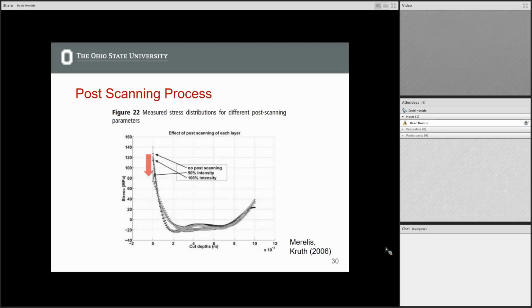However, with 50% laser power, they did see a reduction in the maximum residual stress that was in the part itself. This paper was from 2006, so there may be more research that has gone into these kinds of in-process annealing with the part itself. This is where they kind of ended it, saying more research needs to be done to understand the optimization methods for being able to do this with actual commercial methods.